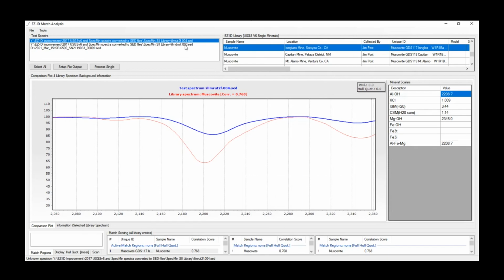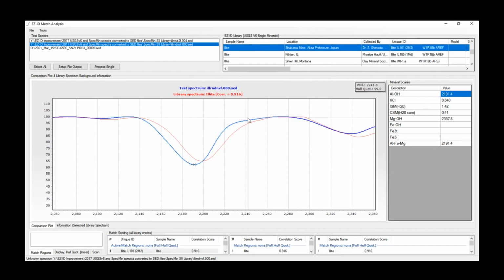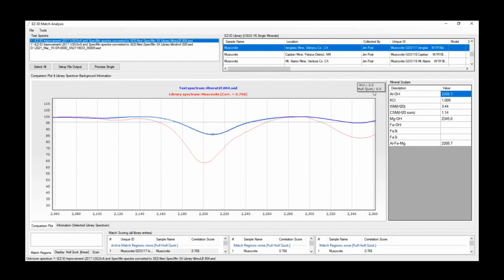So if I go back to the second one, we've got a shift to the left. We've also got a lower ISM score here. So this is indicating that we've got a low metamorphic grade illite, and this one is actually closer to the smectite illite range. Whereas if I go back to that first sample with a high illite spectral maturity, this is actually indicating that this is more on the muscovite alteration of illite. So you can really track the alteration of illites, going from smectite as the illite dehydrates into your micas.